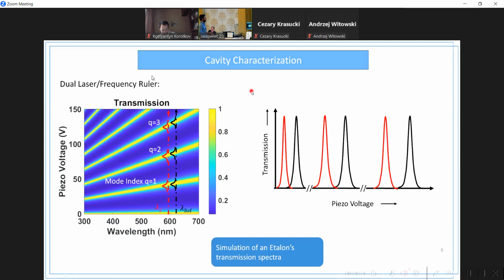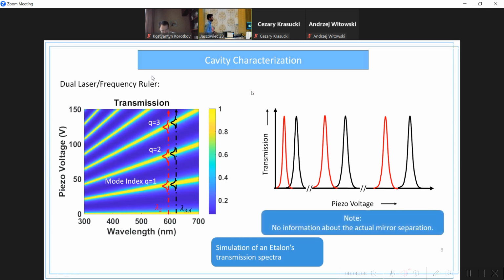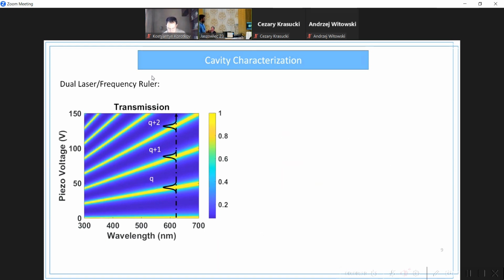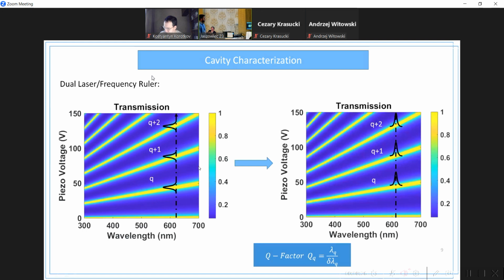So you can already see the problem here: we do not have direct information about the actual mirror separation. On top of that, what we typically measure experimentally is the broadening of the modes in this piezo voltage domain. However, to calculate things like quality factor, you usually require the broadening in the wavelength domain.